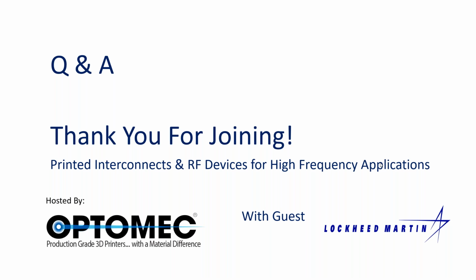We don't have the data in this presentation, obviously, but if you get with me offline, we can show you what we do know. We do have to sinter above a certain temperature in order to get that current carrying capability. And we have to try and keep the transition with the fillet as smooth as possible so that there are no sharp corners or edges that might decrease the cross-sectional area in a certain portion of the wire. So I can't really get into the specifics of how much current because it's too dependent on the cross-sectional area and the length of the wire and the amount of current being applied, and also the max temperature limit of the package.